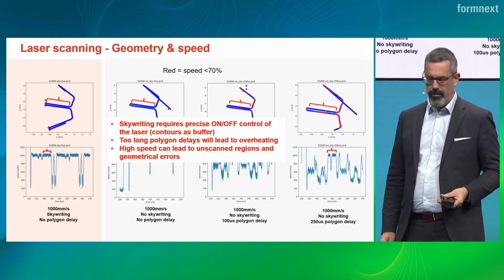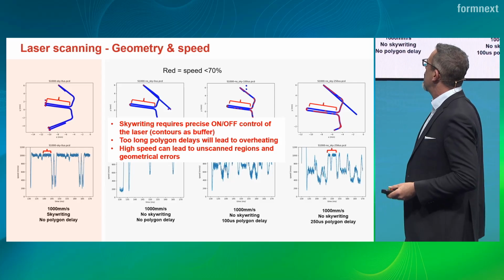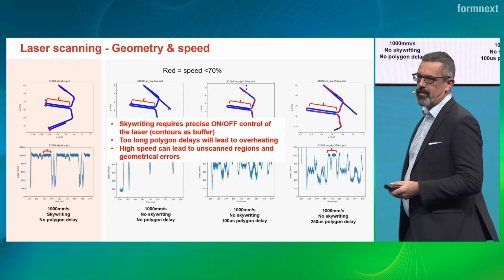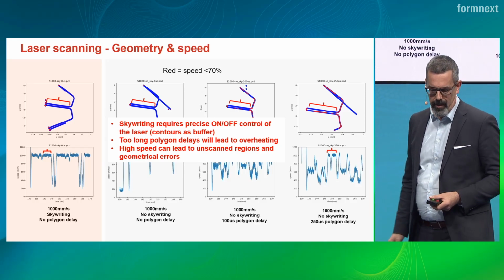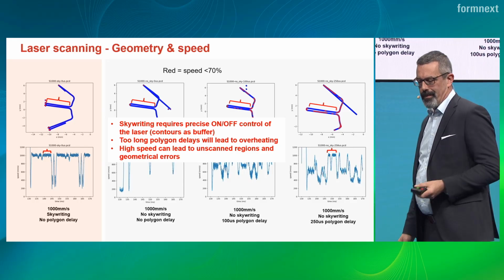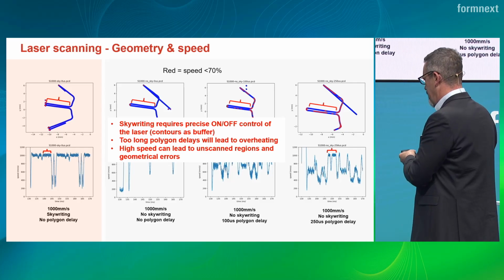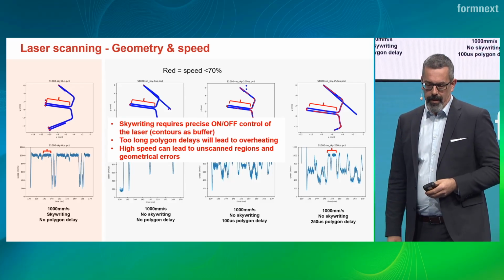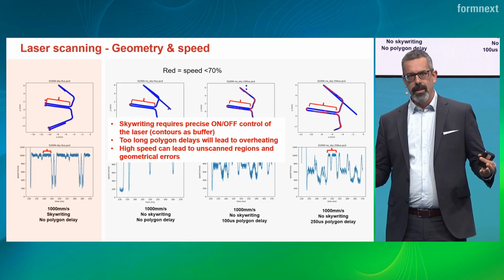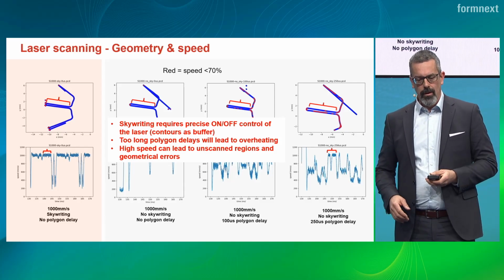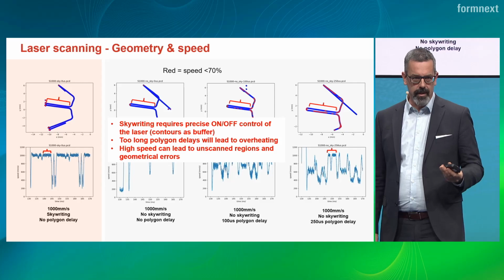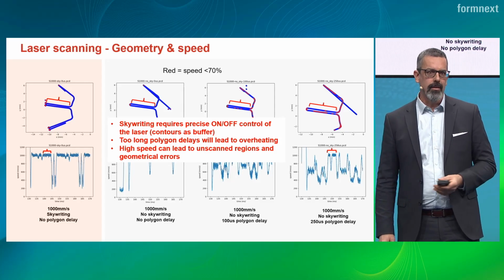So you introduce skywriting on the left, works well. On the right, you have polygon delays that many of us use in recipes, knowingly or not. And you see if there is a polygon delay that is different from zero, these sections where the speed is not met get quite long. So this can lead to an overheating and a failure of a part.